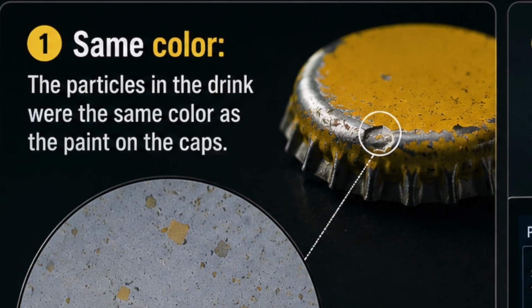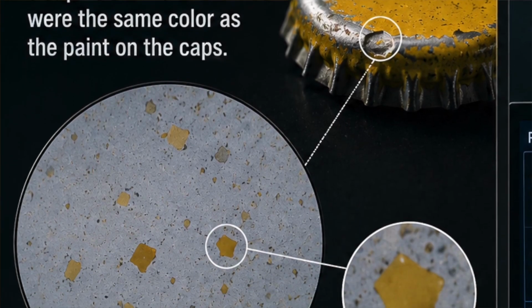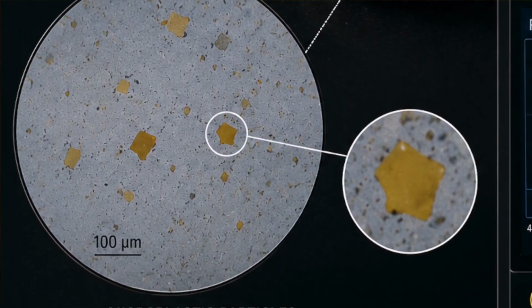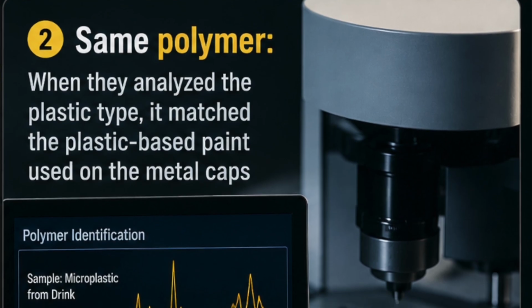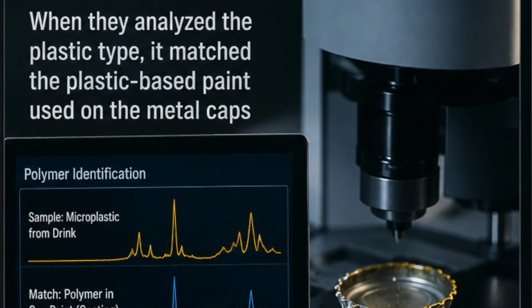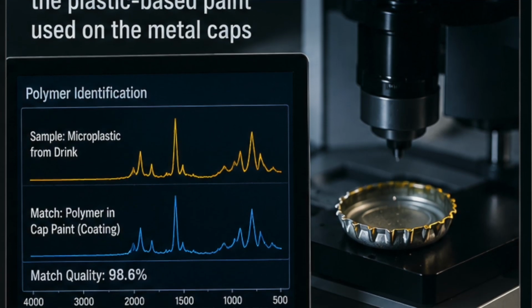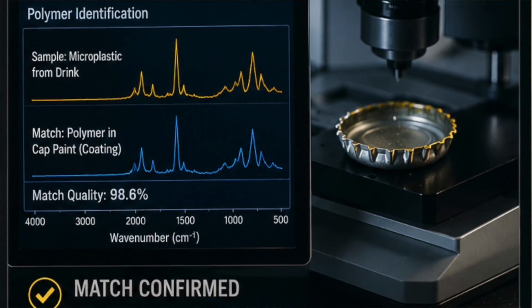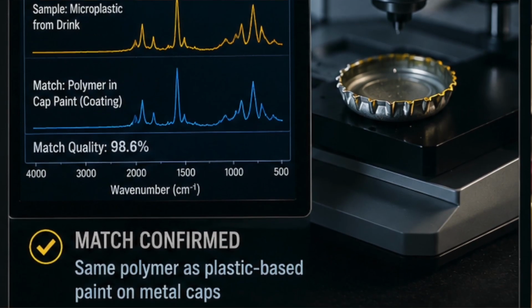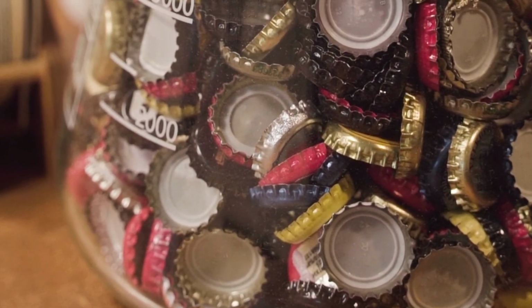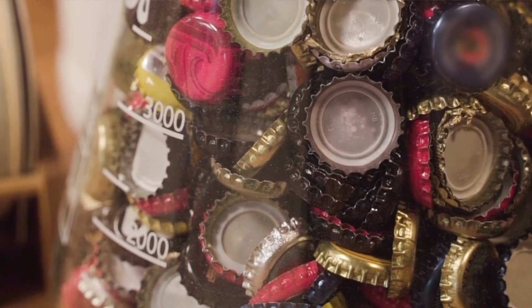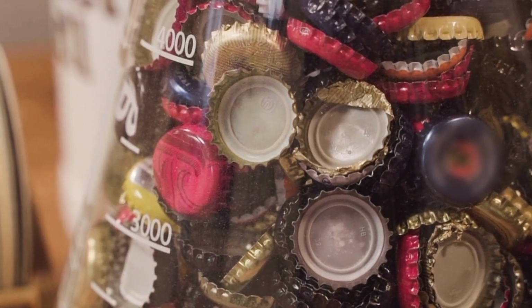So the scientists asked, if the bottle isn't the problem, what is? They took a closer look at the microplastic from the glass bottle drinks. 2 big clues jumped out. Same color. The particles in the drinks were the same color as the paint on the cap. Same polymer. When they analyzed the plastic type, it matched the plastic-based paint used on the metal caps. Then they examined the caps themselves under magnification and found tiny scratches in the paint coating, too small to see with the naked eye.